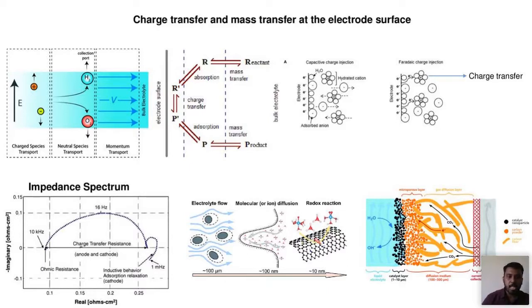There are 3 types of transfer: charged species transport, neutral species transport, and momentum transfer. These can happen at the electrode-electrolyte interface. Mass transfer is a very important property, and you need to control the mass transfer by rotating or stirring your electrolyte to ensure efficient transport of the reactant from the bulk solution to the electrode. And also charge contribution.